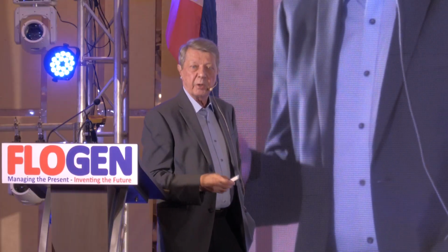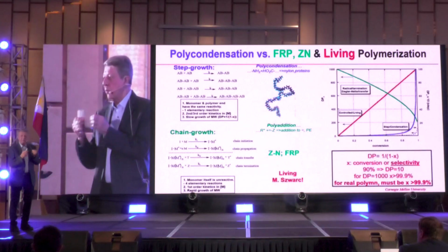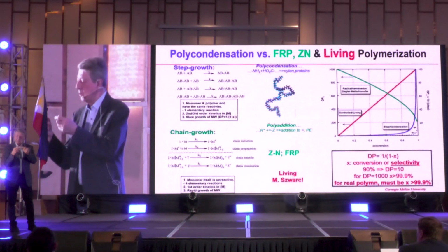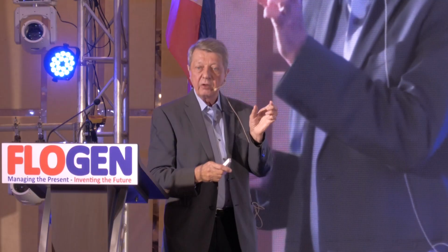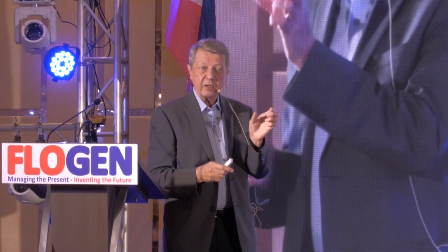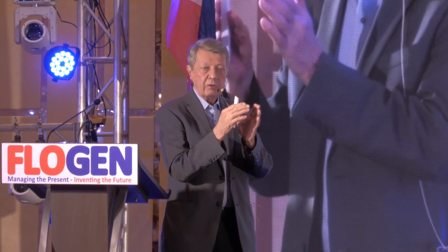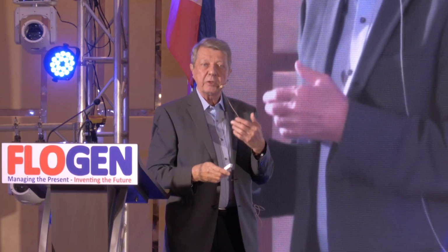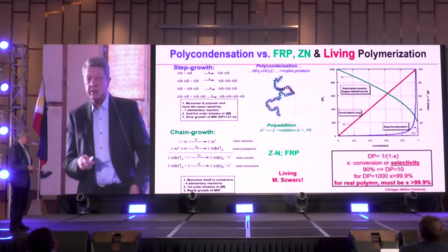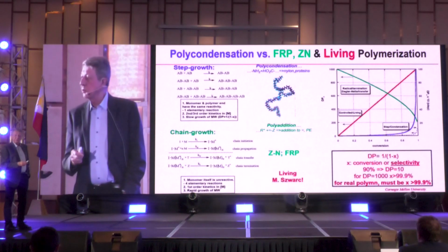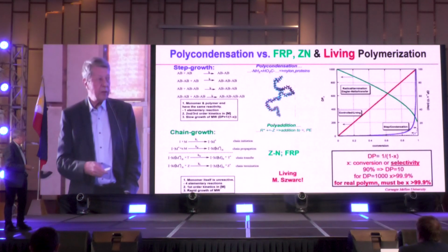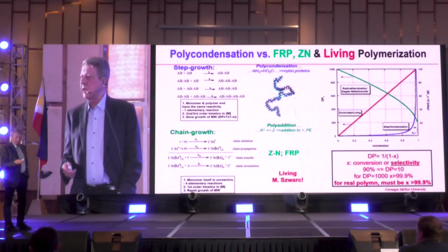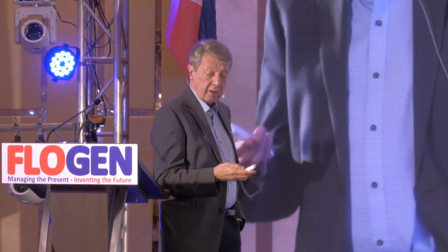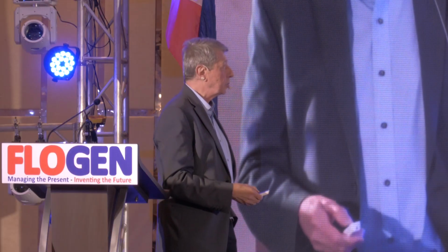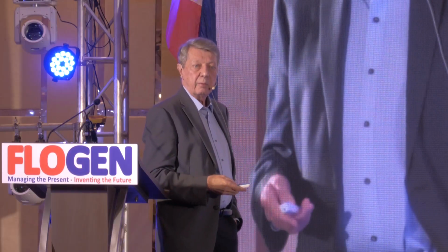This was a revolution in polymer science, because polymers hate one another. They cannot really be together. They phase separate, but if you connect them covalently, in that case, they phase separate on the size of molecules, on the nanoscale. So this was the beginning of nanotechnology, making materials with domain sizes of 5 nanometers, 10 nanometers, with a very regular structure. In that case, this X is not conversion anymore, it is selectivity. It means how many times you propagate before these chain-breaking reactions happen. So this is really the beginning of macromolecular engineering, materials which would be prepared in a tailor-made way.